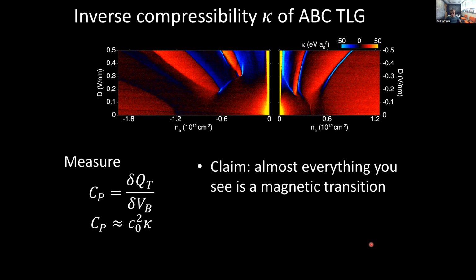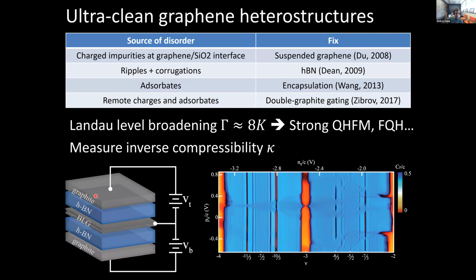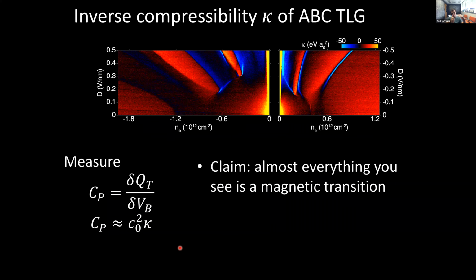Okay, so let me show you the same measurement in ABC trilayer graphene. I'm showing you data now plotted on a color scale as a function of the charge carrier density. So here's electron doping, and here for hole doping. All of this is just affected by changing the DC voltages on these gates, and displacement field, which here is the voltage difference between the top and bottom gates, whereas the density is tuned by their sum. So you can change the total density. You can also change essentially the polarizing electric field. And we measure, and you can read this color scale as being proportional to the inverse compressibility.